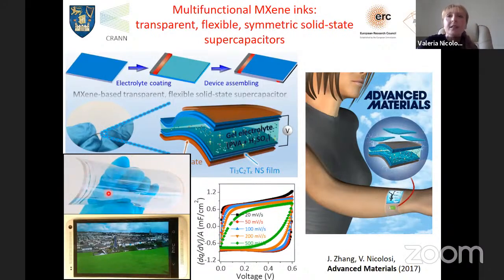This is a full electrode device. This is overimposed on my postdoc's mobile phone to show you really 99% transparency. And this is the electrochemical performance of this device that shows you how it is electrochemically active, even at high scan rates. You can push it up to 500 millivolts per second, which means fast charging, discharging, and you really don't get any resistive behavior. It really works nicely. This was a groundbreaking work for us because it really opened up a lot of possibilities for us.